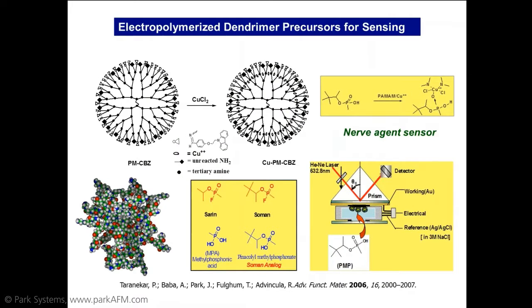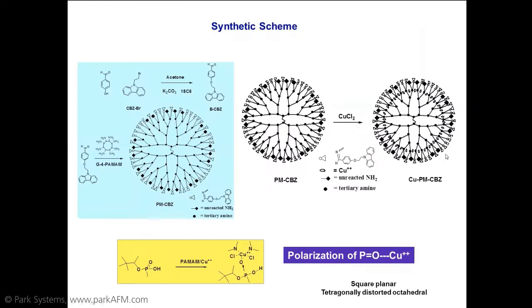So in this case, we actually designed a dendrimeric material, modified it with copper chloride, and at the same time added an electropolymerizable carbazole group. PAMAM, or polyamidoamine, is a commercially available dendrimer. When we load it up with copper and functionalize it through the imine with the carbazole unit, we render this macromolecule electrochemically active. So the idea is to pin this film on an SPR chip, introduce the analyte, and then use the SPR experiment to sensitively detect the presence of, let's say, the model soman or nerve gas agents such as PMP.